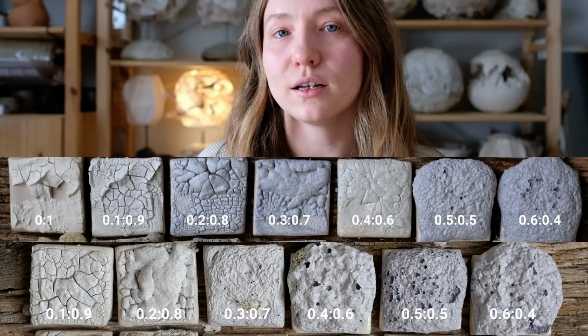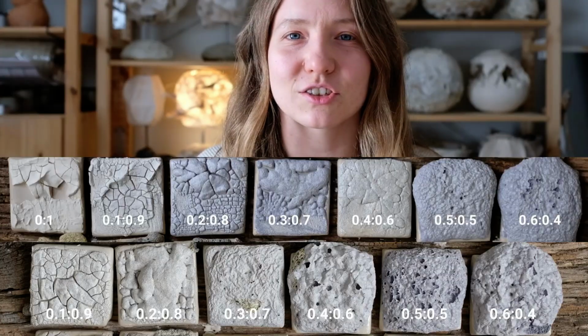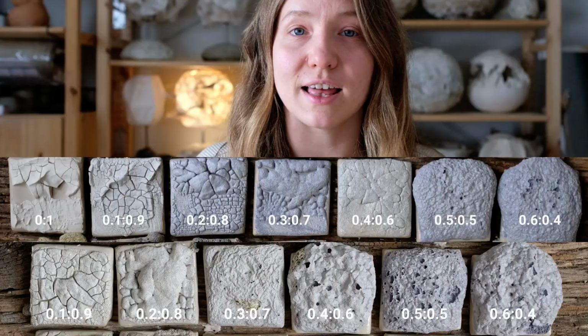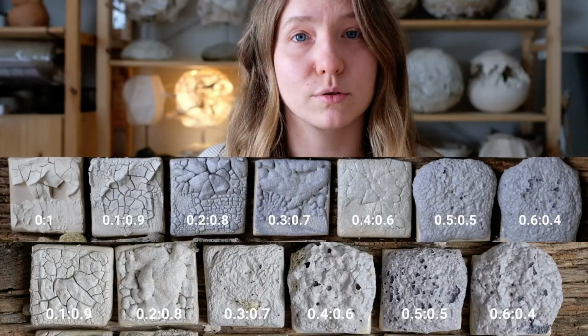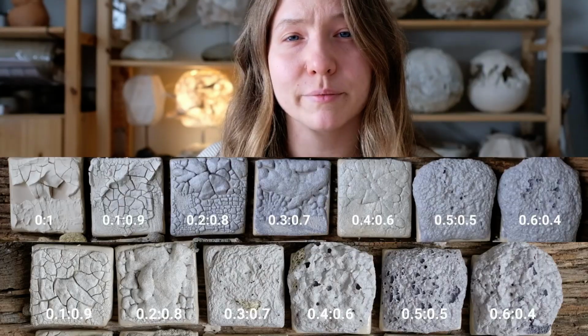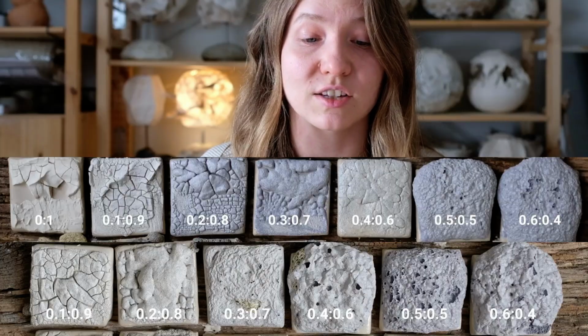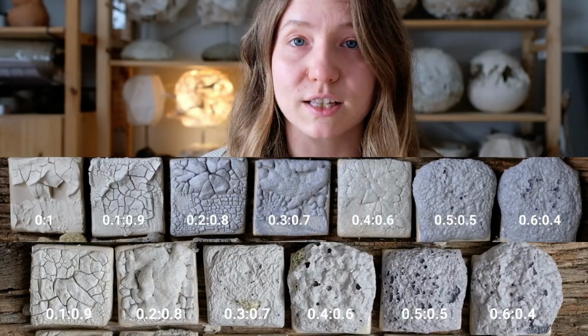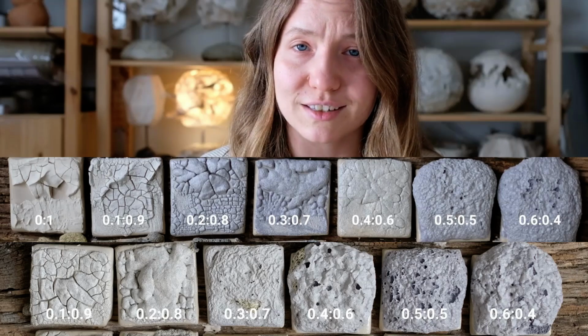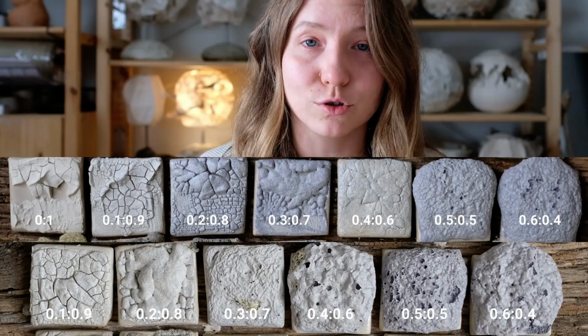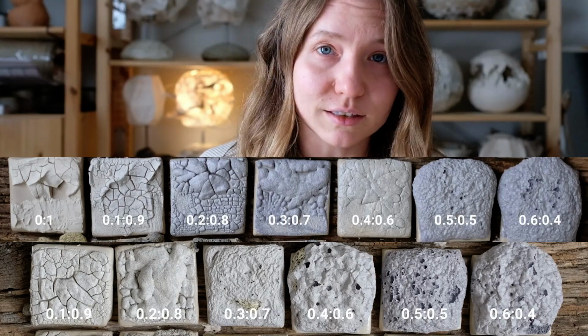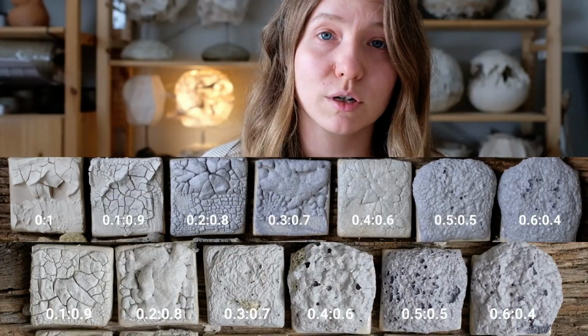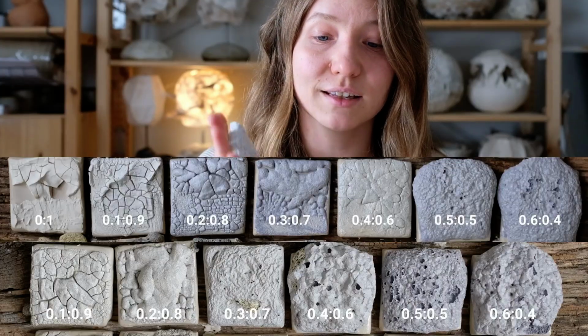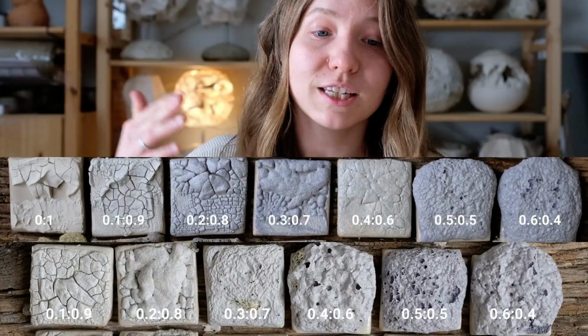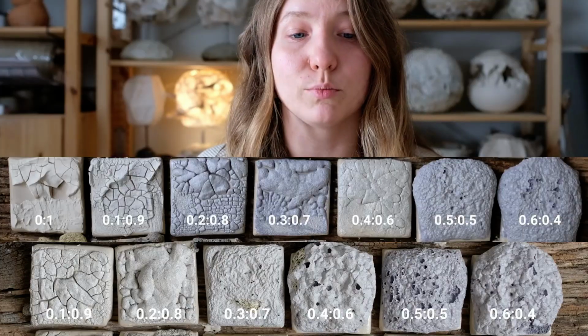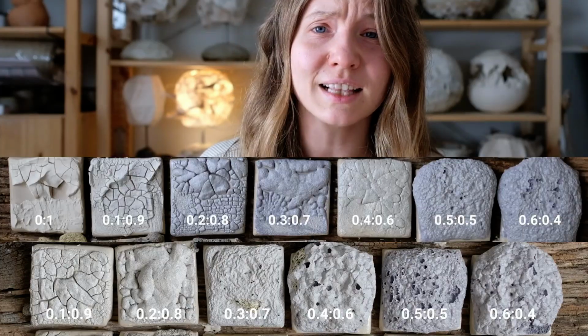As you know, for cone 6 and mid to high temperature glazes, the ideal flux ratio for durability is 0.2 to 0.8, 0.3 to 0.7, maybe a little bit higher, but somewhere within those ranges. And as we can see here, although all of those glazes are underfired, because lava by default is underfired, and the puffy glaze is also underfired, we still get the most durable, the hardest glazes in the middle of the row.